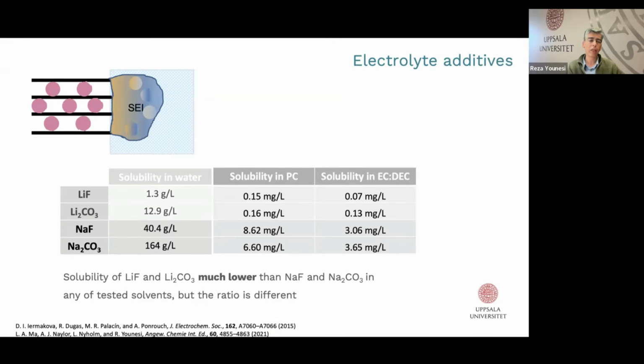What we try to do is add some of this SEI species into the electrolyte in advance before starting the cell. If you look at a few different SEI components, like lithium fluoride versus sodium fluoride, or lithium carbonate versus sodium carbonate, you can see that the solubility of these species is very different depending on what solvent we use. If it's water, of course it's much higher, and it's one case which is very easy to measure.